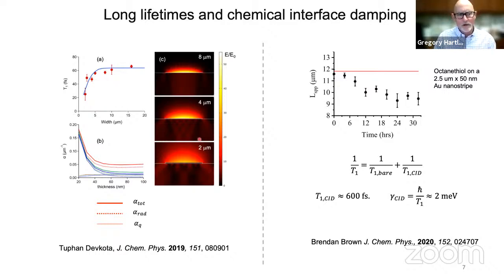Because these things have very long lifetimes, we thought that maybe we could measure the properties of metal surfaces accurately. So one thing that's of interest is to measure chemical interface damping, right? If you put a molecule on the surface of the metal nanostructure, you damp the plasmons. This has been looked at quite a bit for particles, and so we tried to do the same thing for the nanostripes. If we take one of our nanostripes and we add an alkane thiol, we do see that the propagation length goes down. So we see an interaction with the molecules, and we can analyze that to get an effective damping from the molecules, which we call chemical interface damping.